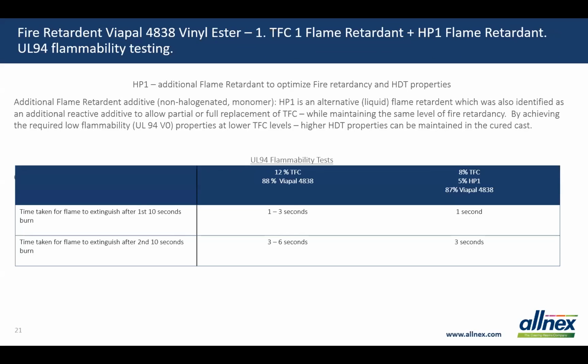This new flame retardant is also a liquid form, so we've maintained those good processing properties potentially for the resin in a pultrusion process. But where this one differs from the TFC is that it's a reactive material. It means it actually reacts and cross-links into the final cured resin structure, so you don't have an effect on HDT. So we basically could reduce the TFC level in the formulation by using this other material in combination.